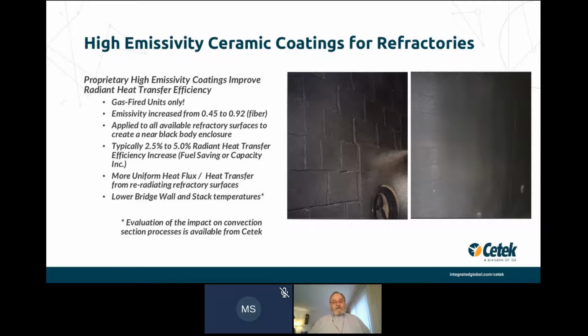That's about as high as you can get using refractory materials. We apply the refractory coatings to all the available surfaces to try to create as near as possible a black body enclosure. And typically the benefit from that is to increase the radiant heat transfer efficiency by up to 5%. Because the refractory surfaces are radiating heat within the enclosure, the heat flux is now a lot more uniform. In a low emissivity enclosure, you tend to get a lot of reflected heat from the flames, so it tends to be concentrated in certain areas within the